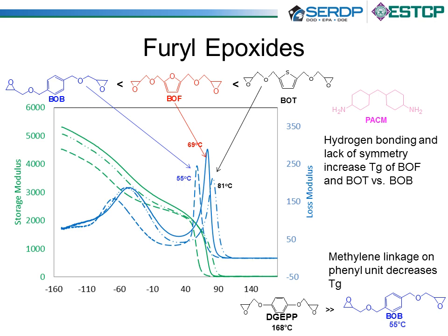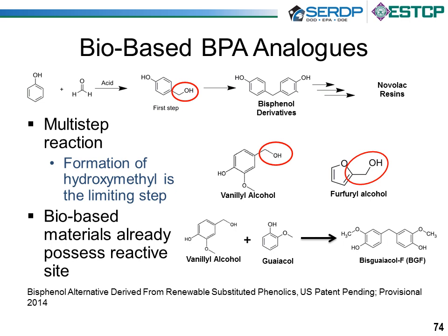Now, on this next slide, I'm talking about replacing BPA, bisphenol A, with basically lignin-derived materials as well as potentially furans. The reason being, when we looked at the synthesis of bisphenol A, basically what happens in the reaction scheme is phenol reacts with formaldehyde under acidic conditions, and it forms effectively a reactive intermediate, this phenol with the methyl hydroxyl group on it, which then can react with another phenol very readily. The addition of that formaldehyde to the phenol is really the rate-limiting step.